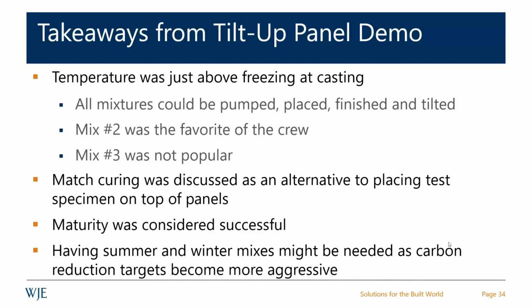All that being said, the crew loved mix 2. That was their favorite. That was the one with the slag cement in it. They absolutely loved it. They despised mix 3. Very difficult to work with. We did use maturity. Match curing, though, was considered something to look at. In all of our future work, we're using match curing now. And one takeaway was maybe have summer and winter mixes. It really was not a good mix to put down when the temperatures were near freezing.